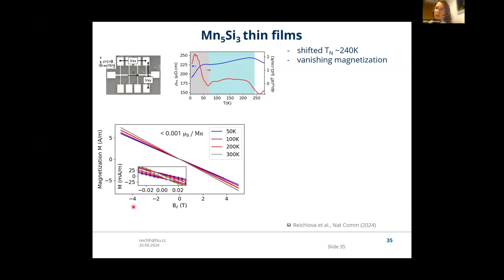So magnetometry of compensated magnets is notoriously difficult, especially when there is a substrate, which we have to somehow subtract. But to the best of our resolution and capabilities, we always try to give an upper boundary to the magnetic moment which we observe. In this case, we give an upper boundary of 1 millibohr magneton per manganese. And importantly, we see basically no change in the full studied temperature range, in the low temperature or the room temperature, which is already above the magnetic phase transition.